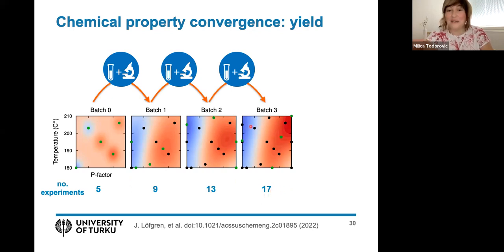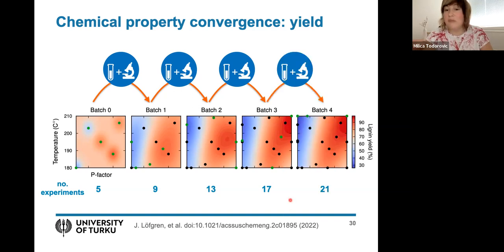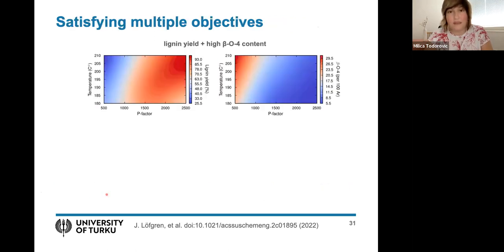And now you can see quite a change in the landscape, in the sense that the maximum yield has moved into this top right area of the processing parameter space. And then when we added the next four, this no longer changed. So you can clearly see between batch three and batch four that the landscapes converged. And this is how we knew we could stop with the experiment. And now we obtained converged surrogate models. So only 20 experiments were needed to converge these models in the search space of two experimental variables.